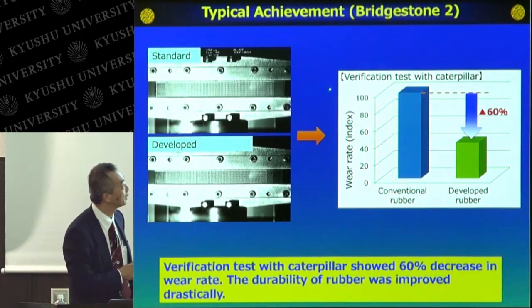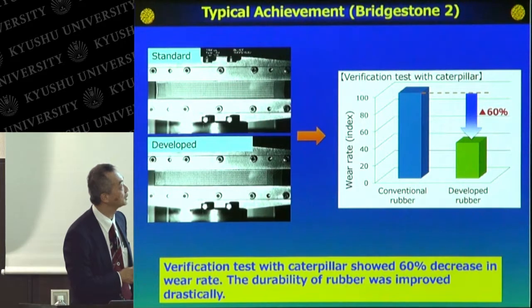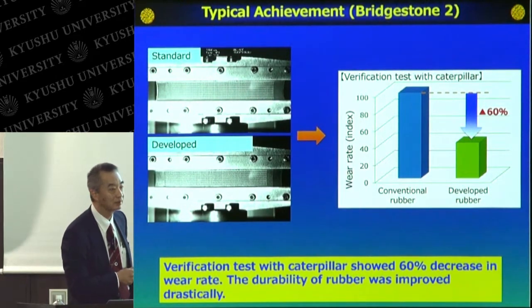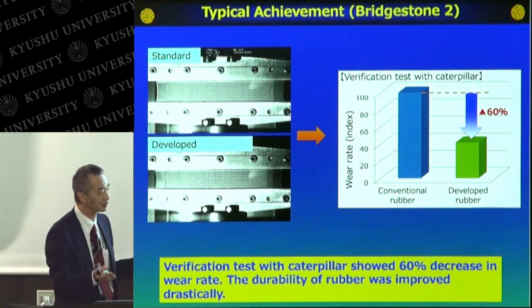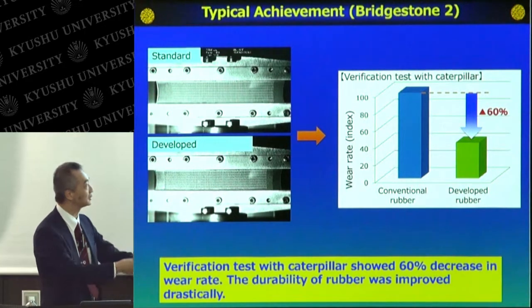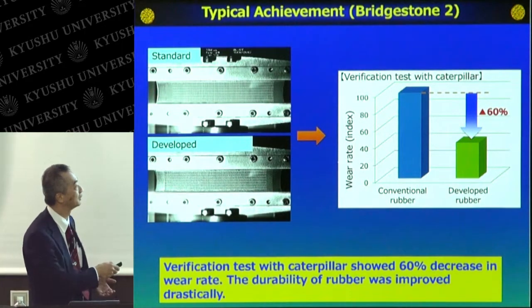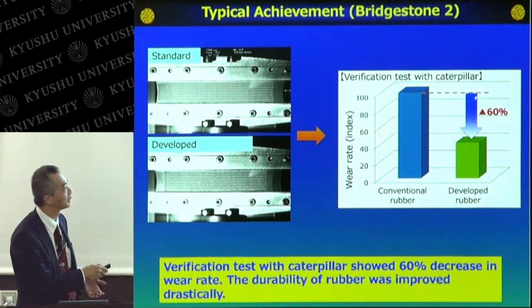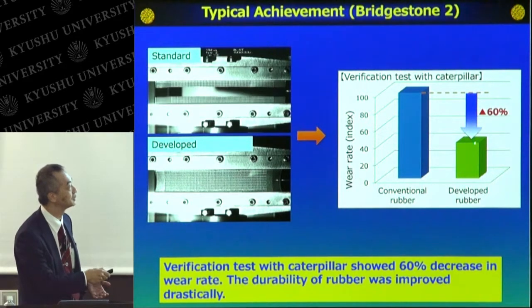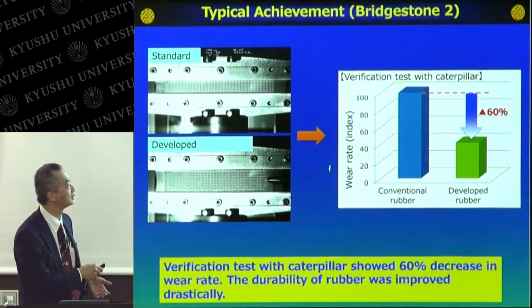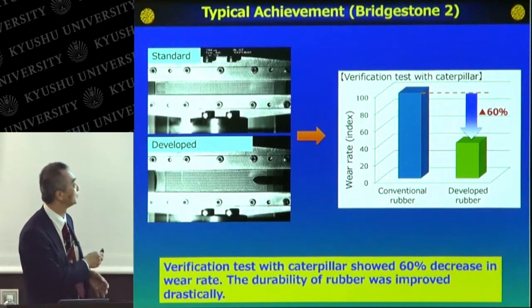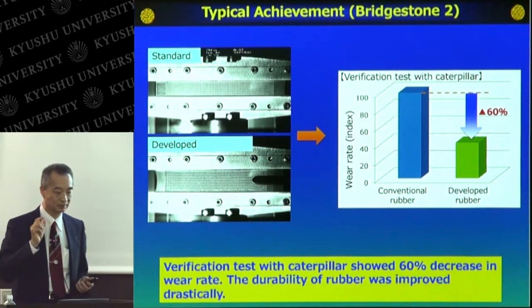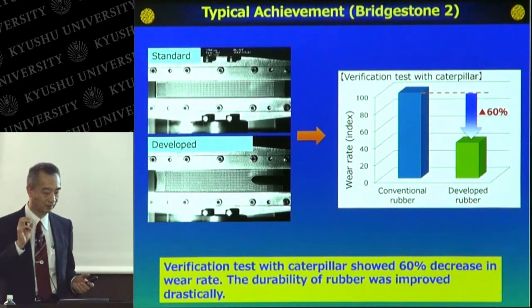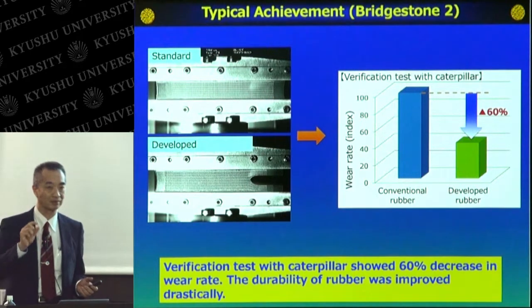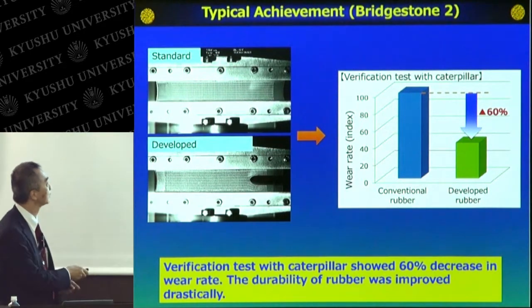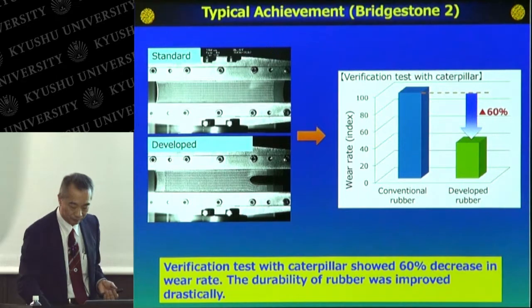So they performed a verification test with a rubber caterpillar. The rubber caterpillar has usual rubber on one side, and the other side is the developed rubber. Then the wear rate is decreased about 60% when they use the developed rubber. So then they can reduce the thickness of the tire by using these developed rubbers.